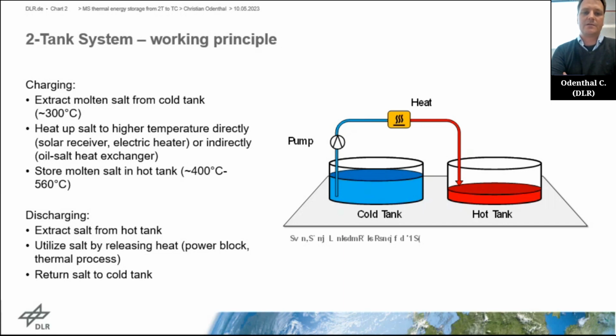And basically that can be done directly in a solar receiver or in oil-based solar power plants. That's done in a heat exchanger, where the heat is transferred from the primary HTF to the molten salt, and then it is stored in a second tank, in the hot tank. If you have an oil-based system, you're limited in the temperature of roughly 400 degrees. These newer solar tower plants go up to 560 degrees. And for discharging, the process is simply reversed. So you extract the hot salt from the tank, divert it to your power block, for example, where you generate electricity, and then you have the salt again at 300 degrees and store it in the cold tank.